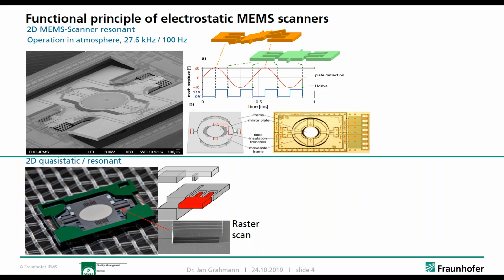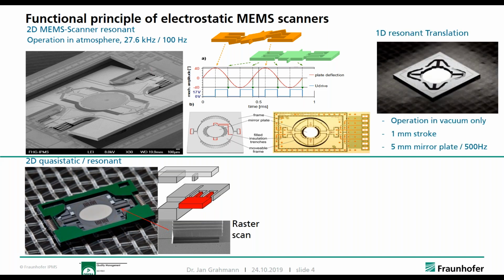Down here, you see just the technology used in order to make a 2D mirror. So these red lines here represent insulation trenches that are needed in order to have mechanical stability throughout the mirror plate. So the pendant practically is seen on the left side, for example. That's mechanically stable, but at the same time, it insulates in between the silicon device layer that determines the thickness of the scanner. And that allows us to make 2D scanning mirrors.